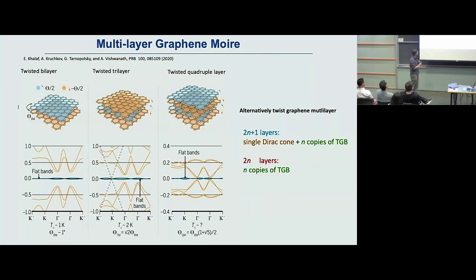And once you're away from twisted bilayer, often that is combined with a so-called dispersive band together. Often in the trilayer, 4-layer, and 5-layer, the displacement field, as we heard, plays an important role because it can hybridize with this flat band. You can modulate the band structures by the displacement field. So the displacement field is an important tool, also at the single-particle level, that can tune these band structures and give us some additional knobs. In fact, using this knob, we can quantify the following argument.